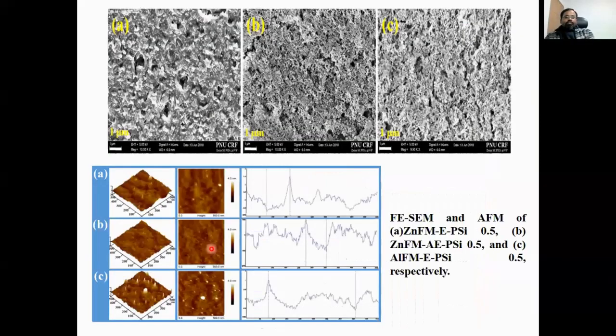And we further checked the amount of silica in that hydrophilic substrate, so we increased the hydrophilic silica content in this coating material. While increasing the silica content in the coating materials, it shows some rough morphology on the substrate, because more silica forms more rough structures on the substrate.